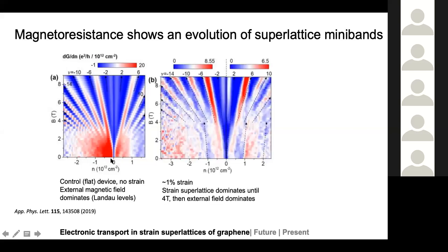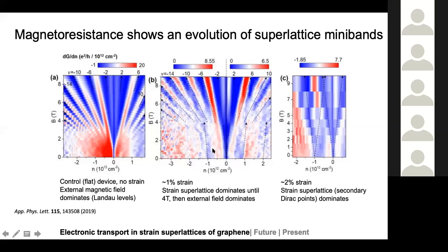What you see is that if you apply the same idea to a system which has around 1% strain, then this additional messy stuff shows up on the side. It doesn't make much sense right now, but it seems like beyond 4 Tesla, the effect of the strain is really not there, and the original fan diagram which you had is again regenerated. However, if you have a higher amount of strain in the system, then you see that these additional fans pop up along with the original fan in the middle, and those fans start from the secondary Dirac point.